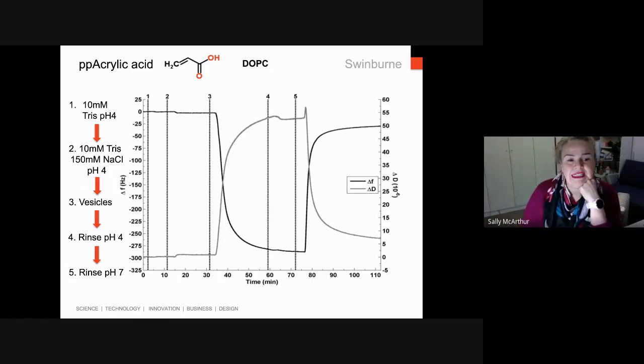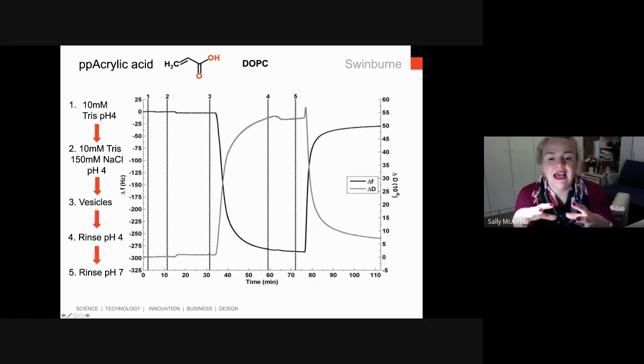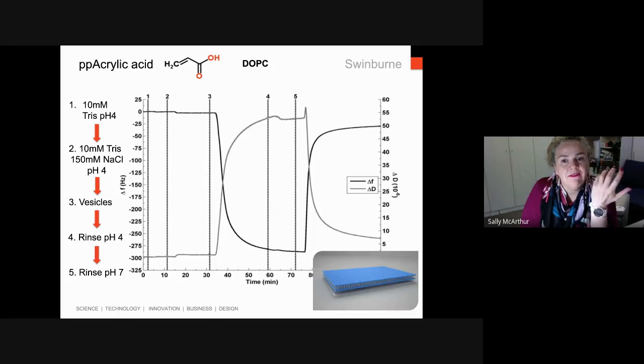And when we rinse this at pH 7, you can see that we rinse off some of those lipid vesicles as well, but we don't ever return. So the vesicles aren't attached tightly to the surface, and they can be rinsed back off for the large part, but we don't ever return to having no vesicles on the surface. So we end up with a few vesicles staying on our surface at that point.